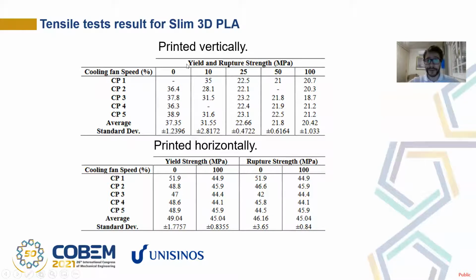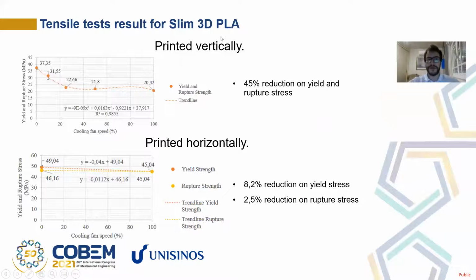The results for the Slim 3D PLA were quite similar, with a reduction for the ones printed vertically between the cooling fan turned off and on at the maximum of around 45%. We can see that the drop happened a little bit quicker here, but the range of values is around the same. And again, the yield and rupture point happened at the same point.